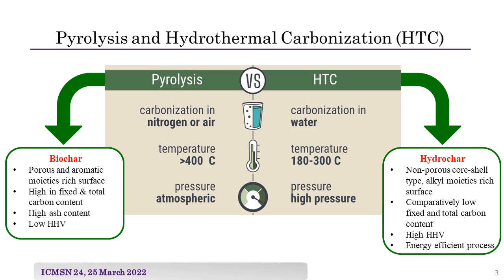With respect to dry pyrolysis, hydrothermal carbonization has different advantages, such as lower working temperatures, lower ash production, and a higher density of functional groups containing oxygen in the solid product. In a hydrothermal carbonization, biomass is subjected to autogenous pressure in a confined environment in the presence of subcritical water, that is, water in the liquid phase at temperatures between 100 and 300 Celsius degrees.